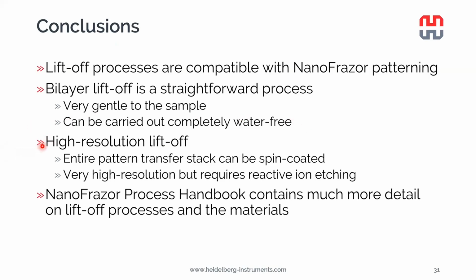I also showed that if the resolution of the bilayer liftoff is not enough for some application, there's also the higher resolution liftoff, where we use a 3-layer pattern transfer stack that can be entirely spin coated. We can reach very high resolution, but it does require reactive ion etching, so it's a little bit more complicated. But actually, if you refer to the NanoFrazor process handbook, which will be an additional feature in the latest software version, which will come out soon, it will contain much more detail than I have shown here about the processes and also all the materials involved.